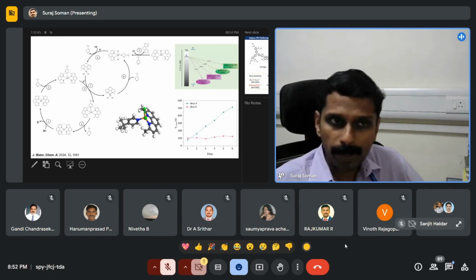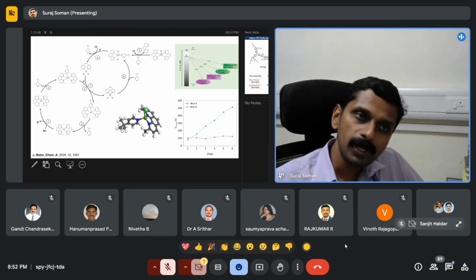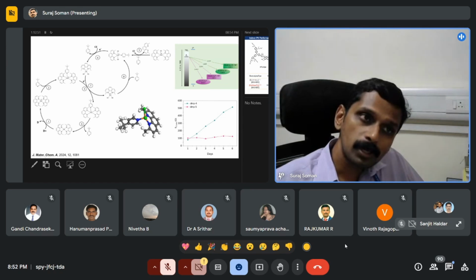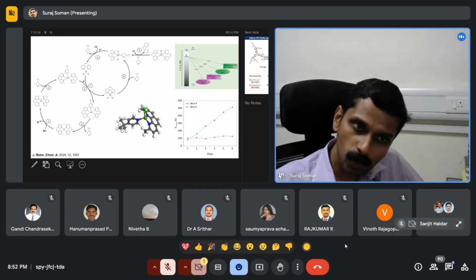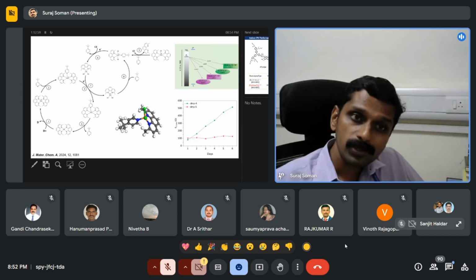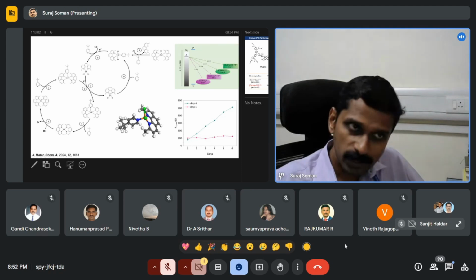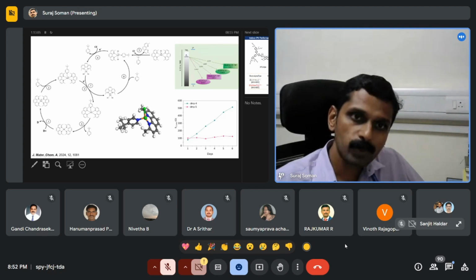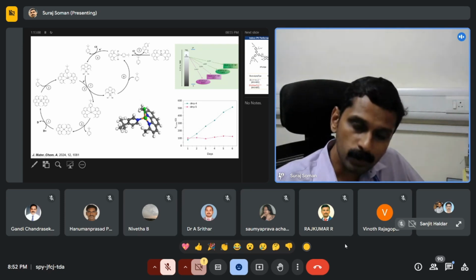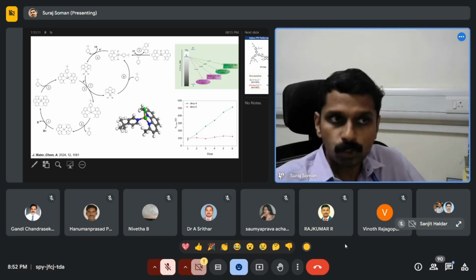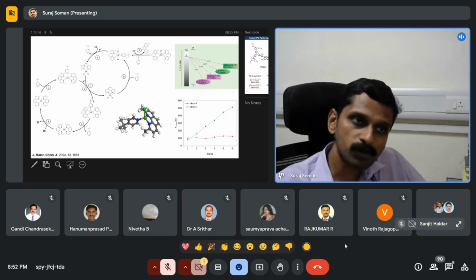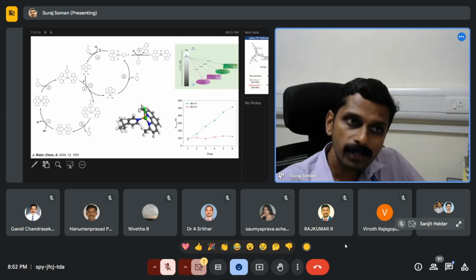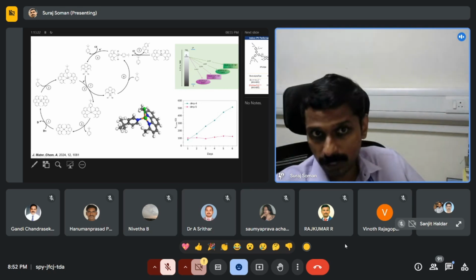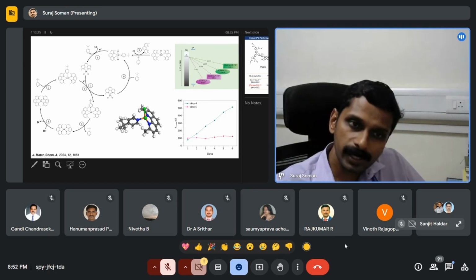But the moment you make this chlorine coordinated system there, what we have observed is that we were able to actually make some intermediate species with a smaller number of tertiary butylpyridine attached to the copper. So how does it help? Because your electrolyte needs to go to the counter electrode, isn't it? Your oxidized electrolyte, once it takes up, needs to go to the counter electrode to take the electron to complete the cycle. So when you are having tertiary butyl groups attached to your molecule, this actually blocks the molecule from getting closer to your counter electrode, not the photoanode, but the counter electrode. So that is actually reflected in the charge transfer measurement.